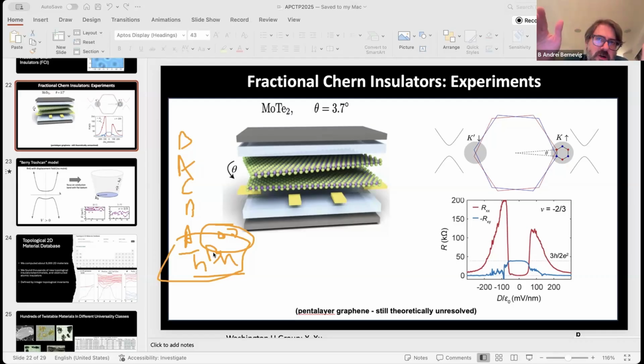One of them, for example, has a curl in the relaxation vector, the other one doesn't. So it's details, but overall, I would expect similar, interesting phenomena. I cannot say that exactly similar phenomena would happen even with lattice mismatch, because relaxation is different. One of them is axial, the other one is longitudinal. But what I could say is that one would expect very interesting things to happen just from lattice mismatch. Okay, good. Yes.